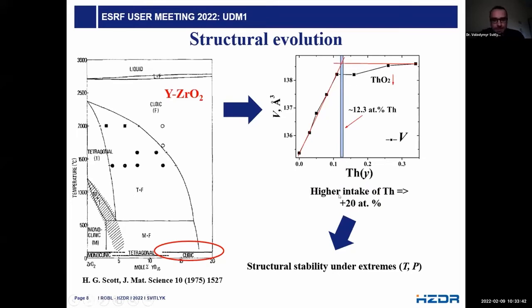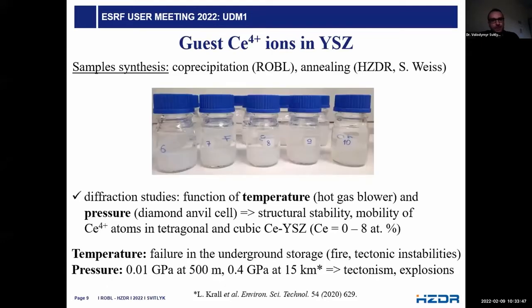So what about the structural stability of these phases under extreme conditions of temperature and pressure? For these studies, we have used cerium 4 ions. These ions are widely used as surrogates for tetravalent actinides, firstly because it makes everything simpler, because they are not dangerous and not radioactive. There is no limit on sample volume and no limit on what you can do. And I was able to perform the synthesis at ESRF in our chemistry laboratory of the ROBL beamline.